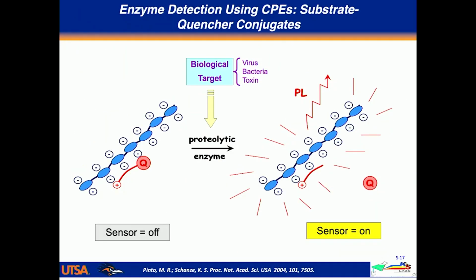Okay, so now I'm going to come back to the application of using this effect in sensors. And some of the first work that we did, it goes back now about 20 years. We published this paper in 2004. And what we were interested in doing was trying to bring this amplified quenching idea together with the polyelectrolytes to do biosensing. And the scheme that we came up with was pretty simple. The idea was that we developed a quencher ligand, where the ligand is a substrate for some protein that can act as an enzyme. The ligand has a positive charge that delivers the quencher to the polyelectrolyte. And so in this form, the system is off. There's no fluorescence.